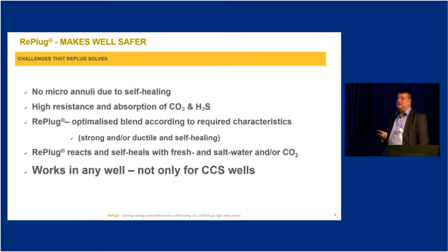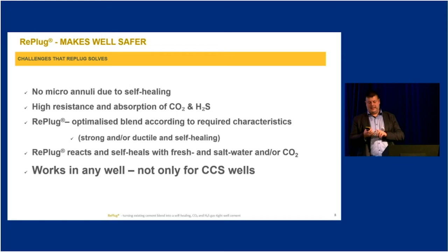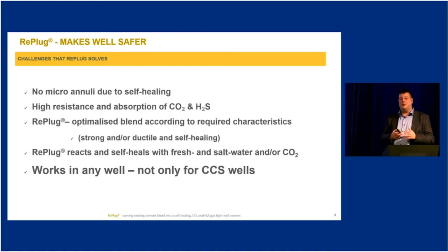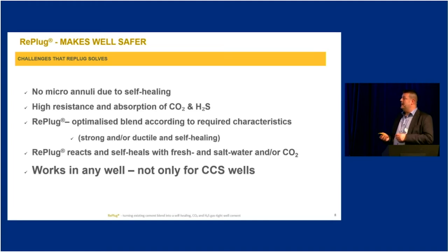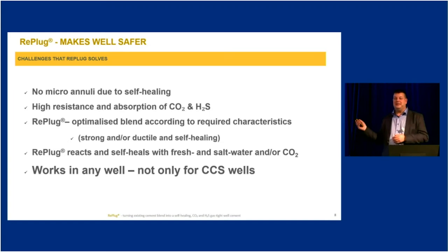And we are able to custom blend — meaning that depending on what characteristics you want on your cement, whether it's high tensile strength or high sealing capabilities, or whatever properties you are actually looking for, we can do that by varying the amount we use in the cement and also the grain sizes we use. So it all depends on what you need for your well cement. And of course, it self-heals — and the most important takeaway is that it self-heals with water. Brine, salt water, water coming naturally from the ground. You don't need the CO2, but it just reacts faster with CO2.